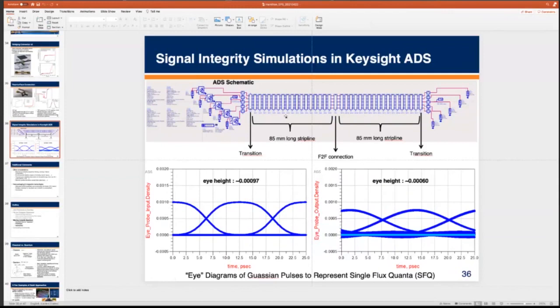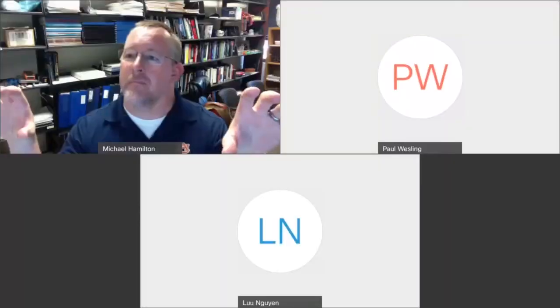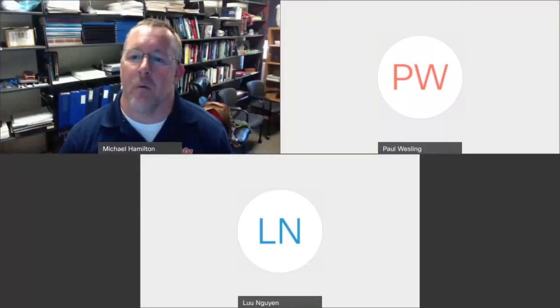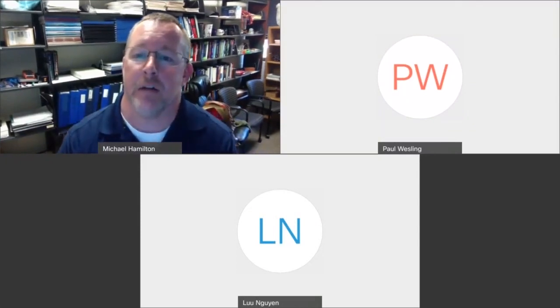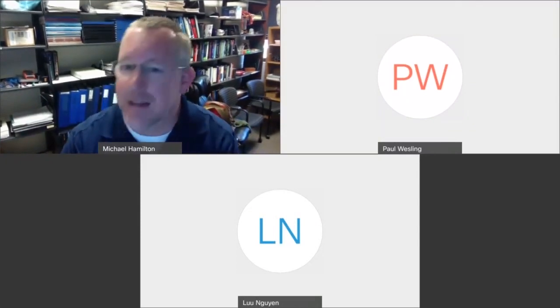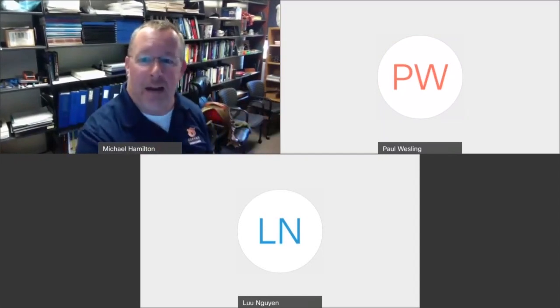We did do a lot of work on those barrier layers. Some of the best results we had were with aluminum. If we did aluminum, niobium, aluminum, and then cured polyimide on top of that, it's hard to figure this out, but I could imagine that the aluminum has just converted to aluminum oxide, and then it protects that niobium. It's not a nice dielectric. Whereas with the aluminum oxide barrier layers, you're just getting aluminum oxide to begin with. I'm not quite sure I answered your question. We actually didn't do a whole lot with Ti.